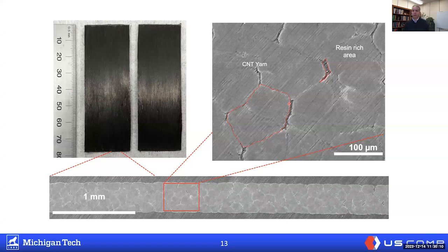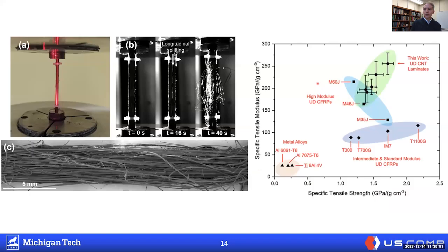And I told you earlier, they're not only flexible in terms of bending the yarns, but they're flexible as far as their cross section goes. And with carbon fibers, you're pretty much stuck and pack those so tightly. But with the carbon nanotube yarn, with its flexibility, you can pack it even tighter. You can even take up a lot of these little spaces. You can see the resin-rich areas are tremendously reduced when you're using a carbon nanotube type of morphology in these composites. So we still have resin in between them for the load transfer, but we get rid of the resin-rich regions, which means we can drive up the volume fraction and drive up the material properties, including stiffness, strength, and toughness.